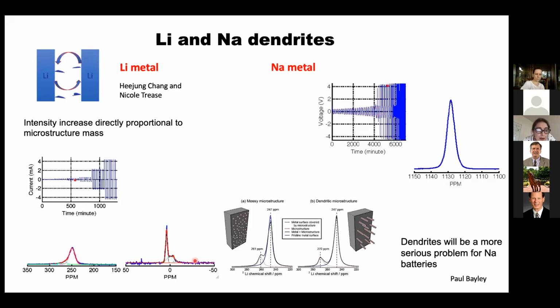And at the same time, you can watch what's going on at 0 ppm, and that's the electrolyte, and this is also the passivating layer. And you can see that once you form a dendrite, that dendrite then gets covered in this passivating layer, and so that signal goes up. And at the same time, you can see that the sodium dendrites have just been going. So sodium dendrite is even more problematic.